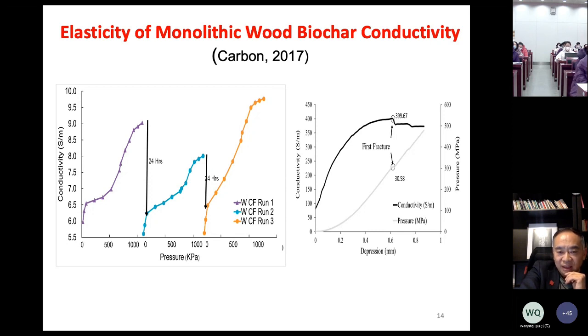Okay. And on the right-hand panel, he's looking at what happens if we apply pressure so that we compress the piece of biochar. What you can see here is that the conductivity increases with pressure, and also that if the compression is over certain values, the conductivity actually decreases. In this case, that is due to the formation of micro cracks under those pressures. Okay.